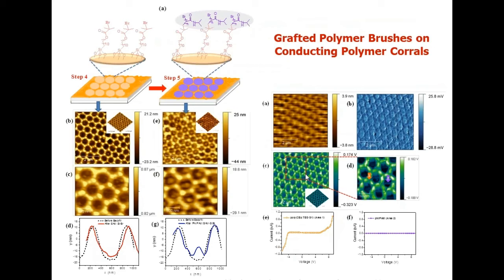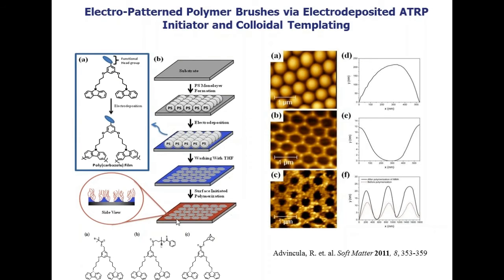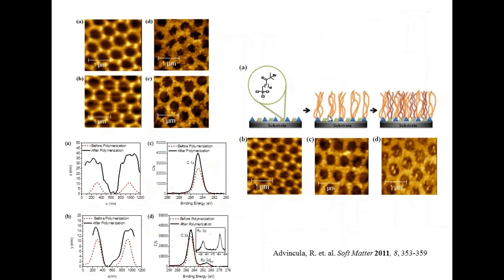Now we can do this chemistry by combining the electropolymerizable macroinitiator. So instead of having a polymer brush in the middle, we can have a polymer brush growing on the ridges, and this has been demonstrated on two different chemistries, but at the same time we can still grow another set of polymer brush in the middle. So this is the case of a polymer brush and a polymer brush on the same surface of two different compositions.